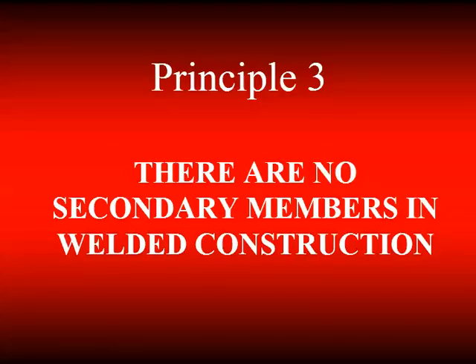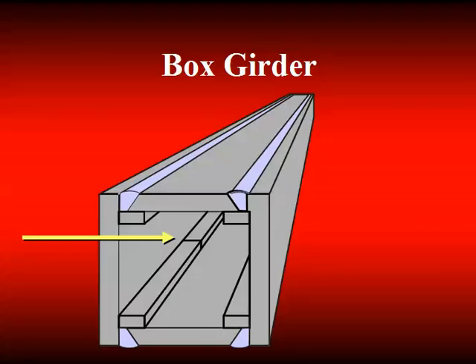Principle number 3, I've said this before, there are no secondary members in welded construction. There's a problem waiting to happen with this box girder. Somebody specified CJP groove welds in the corner, probably didn't need CJP groove welds in the corner, but they did. Now, if we have CJP groove welds and they're made from one side, we use pre-qualified details, we have steel backing, and here's an interrupted length of backing. Now, the designer didn't consider the backing as part of the structure, but when it's joined by a weld, the backing becomes part of the structure.